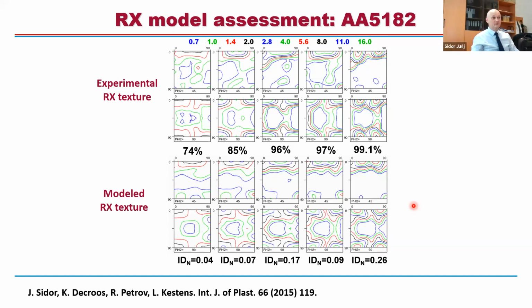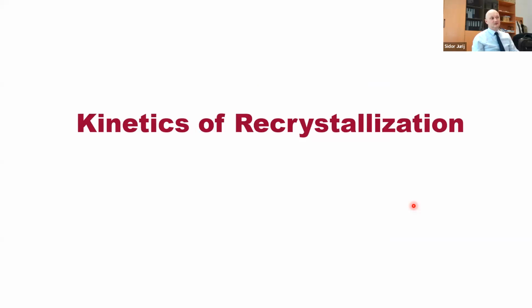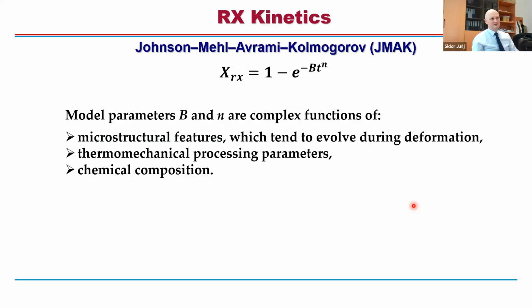In fact, this model works. There is one drawback. The model does not include any kinetics. So therefore, it's important to study the kinetics of recrystallization. Normally, the kinetics of recrystallization is addressed by the well-known Johnson-Mehl-Avrami-Kolmogorov equation, which is almost 100 years old. However, we still did not resolve all problems with this equation, and I will explain you why.